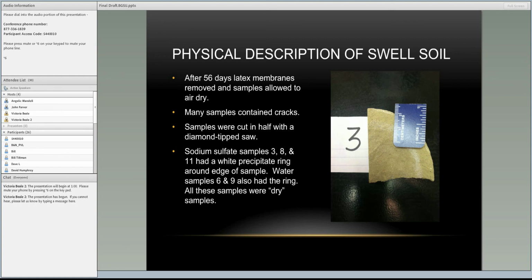And with the SEM, looking at the SWELL samples, it didn't matter where we sampled from. With the SEM, we could find the ettringite needles in the white precipitate area or from the bottom, middle, or top sections. And we also found ettringite needles even in samples 1 through 4 from station 730 plus 80 that had a very little amount of SWELL.